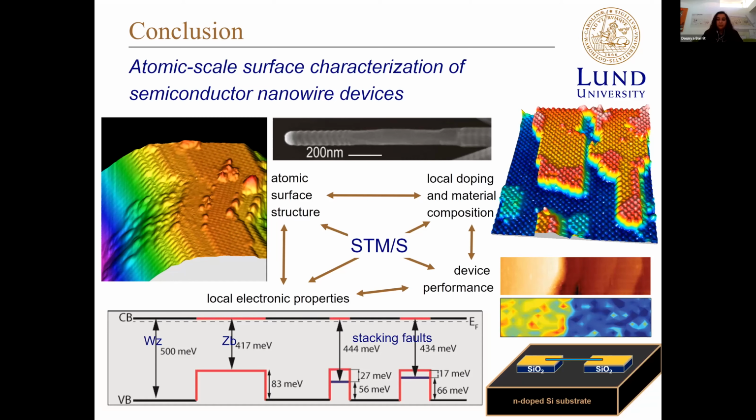There is scanning tunneling microscopy, that is such a scanning probe technique, where you really are in very close contact to your sample. So you have a few angstrom above the surface, where you move your probe along the surface and measure the tunneling electrons. So with that, you are again sensitive to topography, but you're only sensitive to really the surface structure. Scanning electron microscopy probes the entire structure that you see. Here we only get our signal from the topmost 1, 2, 3 atomic layers, and we can look at the local density of states as well.